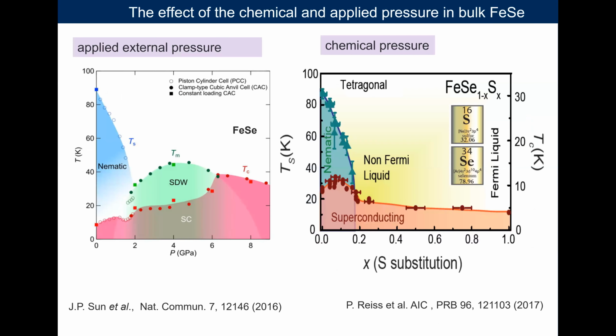With pressure, clearly there are some other important ingredients. So we see that initially applying pressure to the system reduces its unit cell volume. We suppress superconductivity. There's a tiny little dome of superconductivity there. And the same thing happens when you use chemical substitution. This is because sulfur is smaller than selenium, so in a way it has an equivalent effect to applying pressure to the system. But afterwards, after this nematic phase is suppressed, the two systems are not equivalent anymore. That means there are some additional ingredients occurring under pressure.